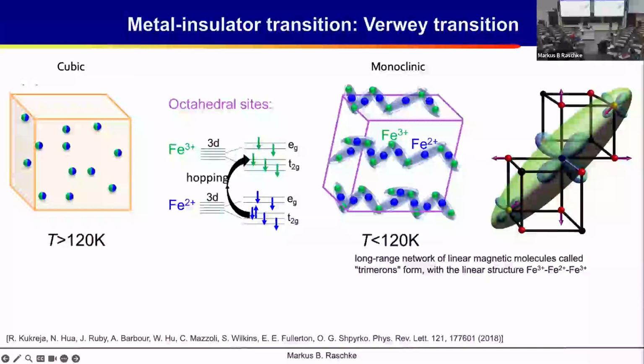And so what happens at low temperature is that the crystal structure changes. So it's no longer cubic. We will have a change in these crystal angles. And so this unit cell distorts. And then this distortion actually leads to a different interaction between these iron cations. And this was only worked out less than 6-7 years ago,